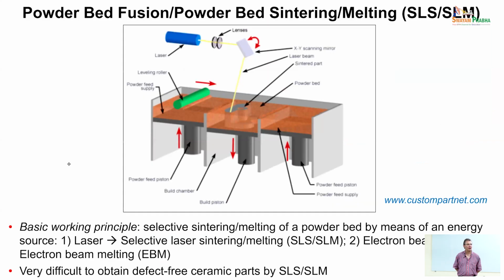So powder bed fusion or powder bed sintering is a very good technology for polymers or for metals, because you can in situ melt or sinter particles, and in the end you can obtain a fully dense body. For polymers, this works rather well. For metals, you have issues in terms of the microstructure, but certainly you can get nice parts with it. You can also use an electron beam for melting rather than a laser. This technology, of course, is again based on depositing flowable powders. In this case, since you are melting in situ, you can reach full density, despite needing a flowable powder.